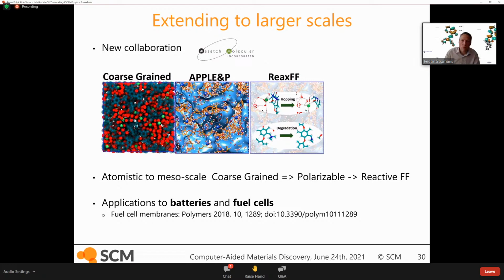And more recently, we have a number of interesting applications using ReaxFF, where you can study, for instance, cross-linking reactions and then look at the cross-linked polymers and try to understand their mechanical properties, as well as degradation properties. And there are also a couple of interesting applications, but this is a little bit tougher, for the nonlinear optical properties of these polymers in the context of using them for 5G and 6G applications. So you can use a periodic DFT code, BAND, to do time-dependent current density functional theory, or you can use MD together with the polarizable force fields to get some of the relevant optical properties for those types of applications.